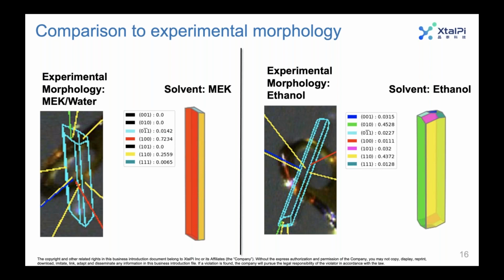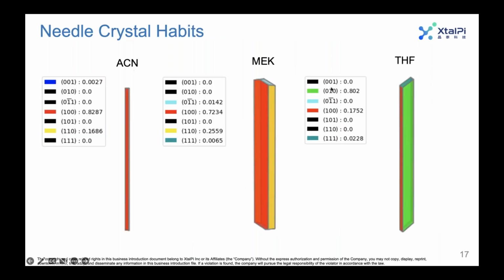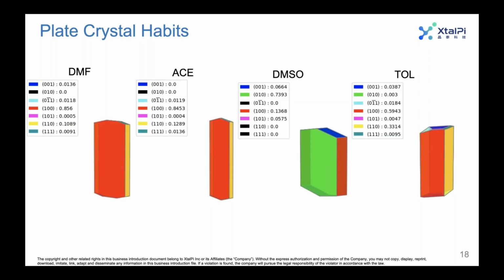So then the next step was to go into solvent systems that hadn't been explored experimentally. So here we have ACN and THF, in both of which we predicted needle-like morphologies. In ACN, we predicted very extreme high aspect ratio needles. However, we predicted different morphologies in some other solvent systems. So we see some plate-like morphologies that are predicted, and even some thicker plate-like morphologies predicted in toluene. So moving into an area of more desirable morphologies, at least the simulations suggest that that should be possible.